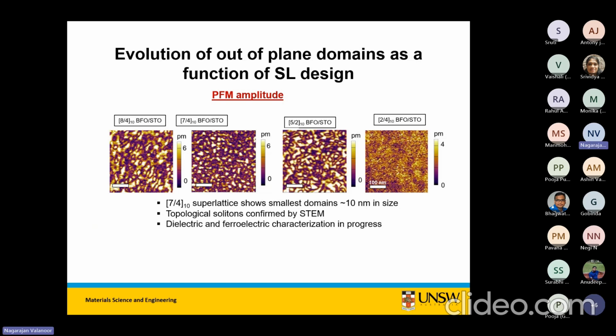If you grow the BFO too thin, then it's actually reaching the point where it's like a smeared dielectric. It doesn't have very good polarization. And I think this is a very, very interesting system itself. So we are going to send you the sample as well, because I think this may be on the verge of some kind of smeared phase transitions. Really something that is exciting, and not many people can do this kind of system.